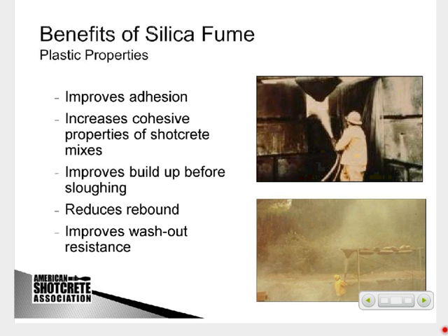The silica fume increases the adhesion to substrates. It improves the cohesion. That's the ability of the material to stick together, and that improves then the buildup before you can slough off. It also tends, because it's stickier, tends to decrease rebound. That's the material that would tend to hit a substrate or a previously shot area and bounce off. That's what we call rebound.